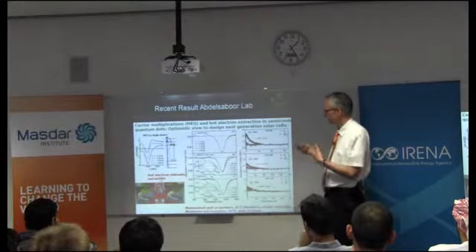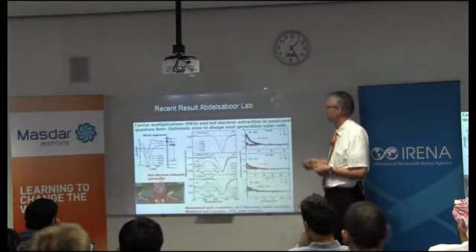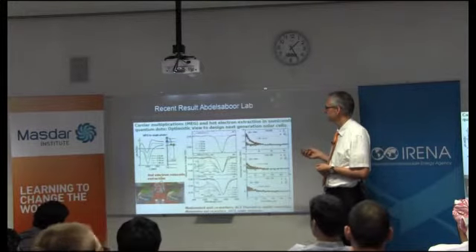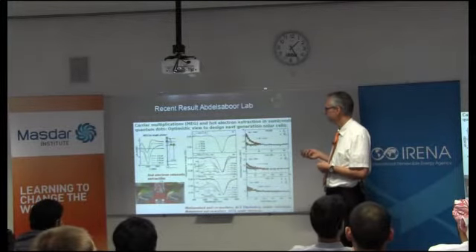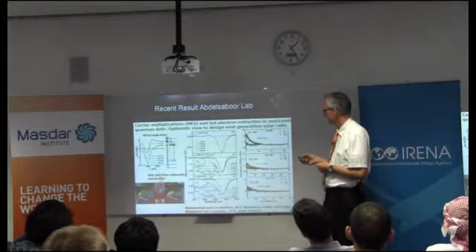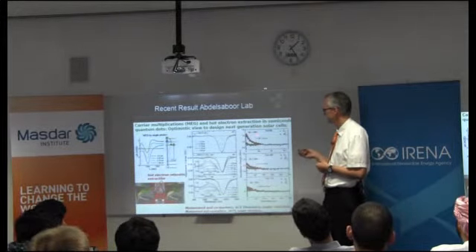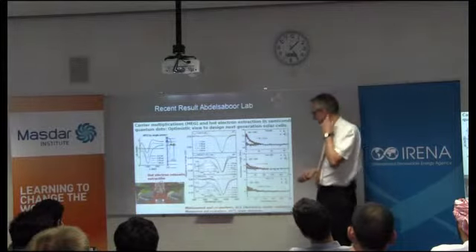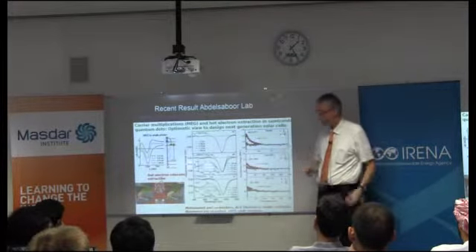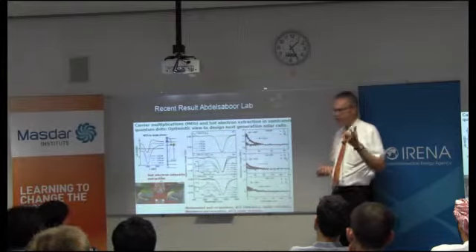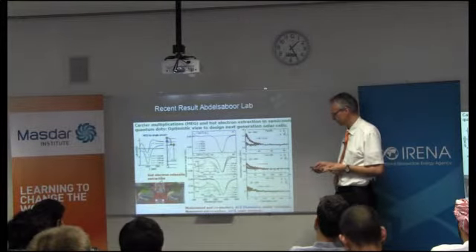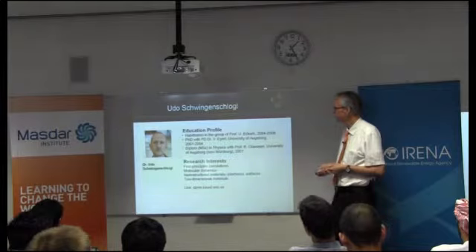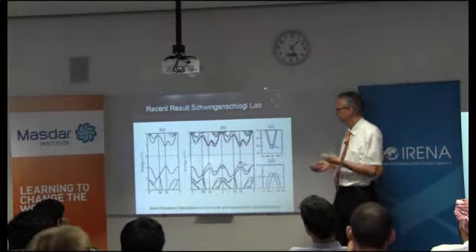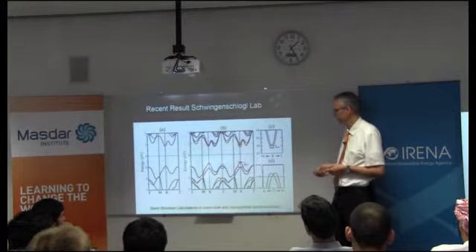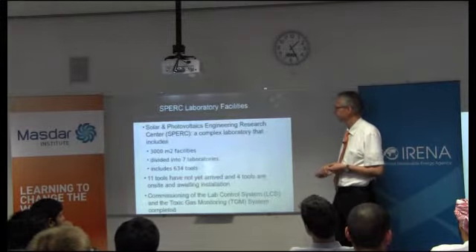This is one result, again a very basic research result. He looked at carrier generation and exciton generation in quantum dot structures, and the very nice effect he saw is that in these structures you generate multi-excitons, and in some cases he had 160% quantum efficiency, so almost 2 excitons per photon were generated. And finally, Udo Schwingenschlogl is a theoretician from Germany who works on density functional, does the theoretical calculations, band structure calculations.